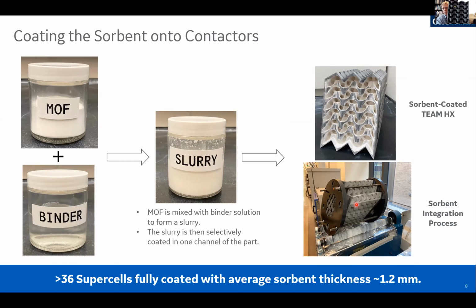This is, again, this trifurcating geometry, where you've got essentially three different faces that are fluidically independent, but thermally connected. And then we can coat this with the process that I showed you before. And so you can see right here, here is the coating material that is embedded in only one of those channels. The other channels do not have that material. And so you can pass through, you can condense the water, you can pass in hot steam in order to drive off the material from those channels.